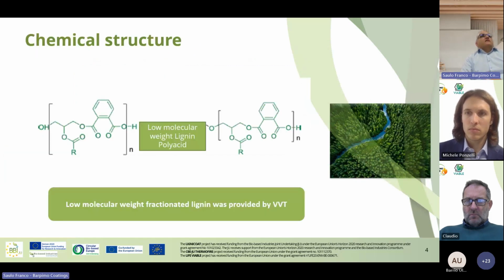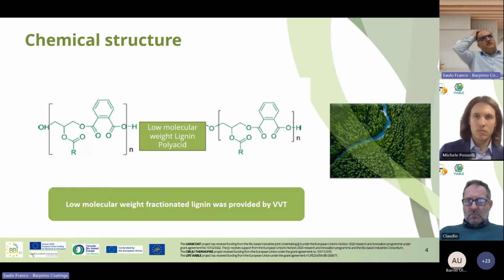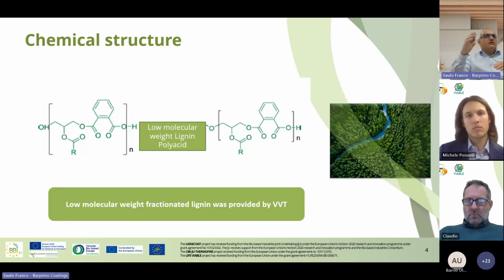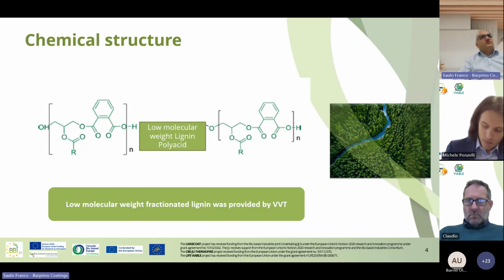So in our case, in this study, we have used a low molecular weight fractionated lignin provided by VTT. VTT provided several types of low and medium molecular size fractionated lignin, and in this case, what worked was the low molecular weight fractionated lignin. So we attached this in the alkyd molecule, and the alkyd formulation was successfully achieved.